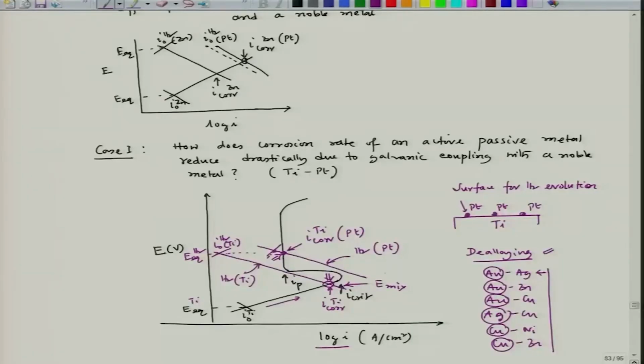Initially, if we follow that mechanism, platinum and titanium both go into solution in the form of ions, but platinum has a much higher reduction potential than titanium ions. So the platinum gets deposited on the surface in the form of locally enriched platinum dots, which then provide a surface for enhanced hydrogen evolution rate. This leads to a situation like what we see in this diagram, and the corrosion rate reduces drastically because the hydrogen evolution rate on the noble metal surface, in case of an active-passive metal like titanium, takes the mixed potential into the passive zone.